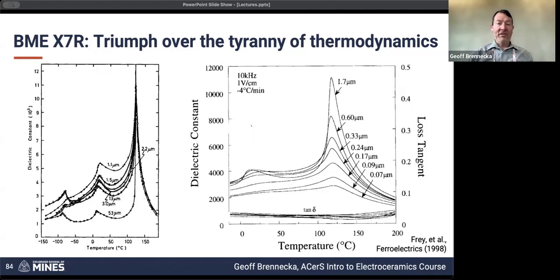All right. So another challenge associated with this, we spent the first 10 slides of this discussion talking about how we want the grains to be as small as possible. We want the layers to be as fine as possible. Well, it turns out that in barium titanate, this is for pure barium titanate, so not the X7R version, but there's a very large grain size dependence on permittivity. So if you look at very large grains, so 50 microns, as you decrease grain size, you see a large increase in the dielectric constant, relative permittivity, at all the temperatures below the cubic to tetragonal phase transition. So the Curie point. So the Curie point is this phase transition between cubic and tetragonal. And so the largest difference is seen for that tetragonal phase, but we still see an increase in permittivity for the other lower temperature transitions as well.